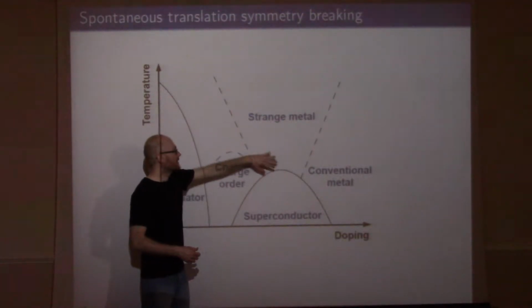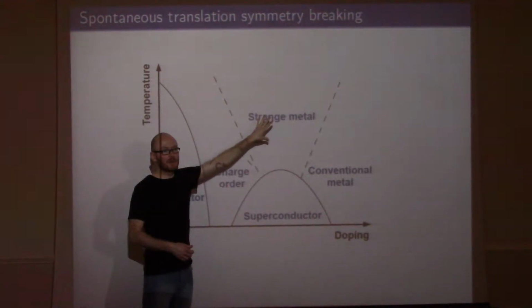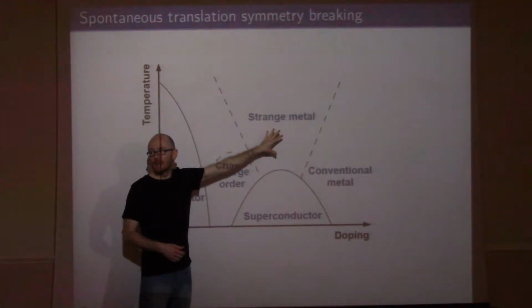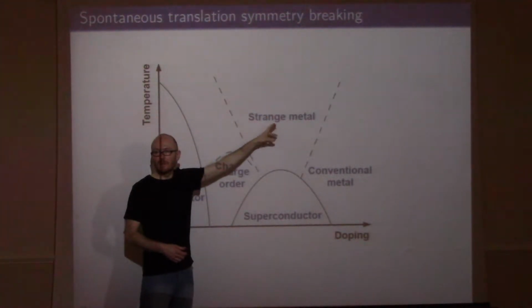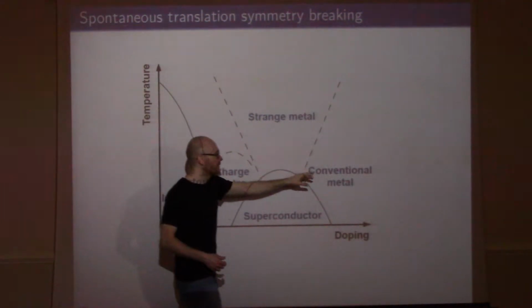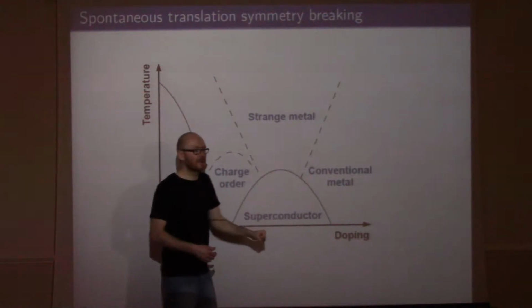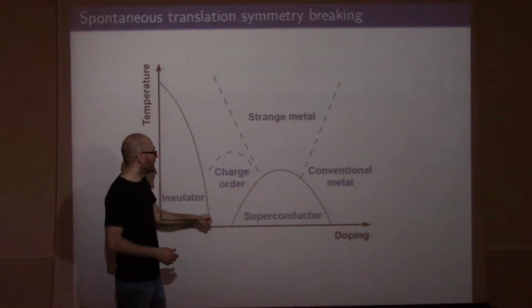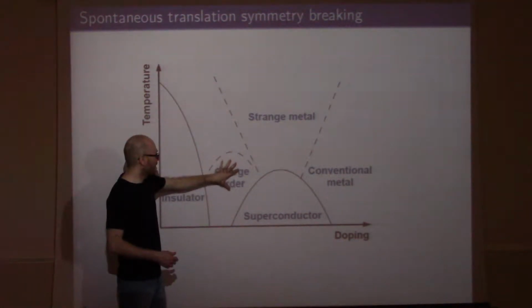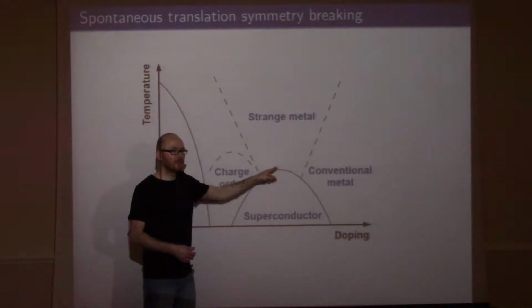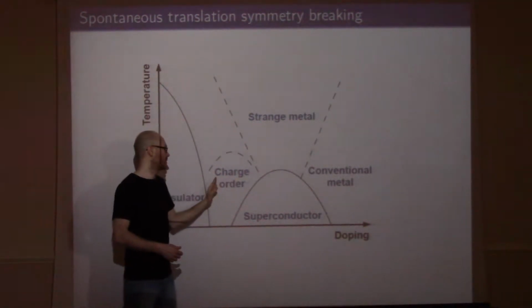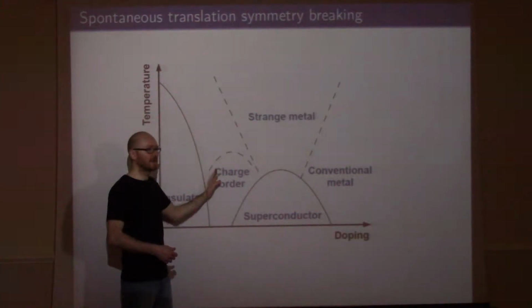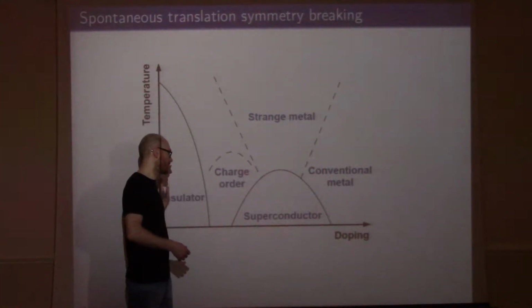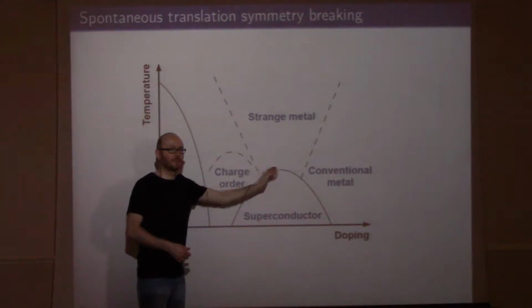Now, above there's this strange metallic phase, which is essentially where all these measurements that I was mentioning are made. This is where the resistivity is linear in T, so it doesn't behave like a conventional Fermi liquid, which is more like this part of the phase diagram. But then here, at underdoping, so this is optimally doped because this is where Tc is highest, and when people talk about underdoping, you're between zero doping and the optimal doping.